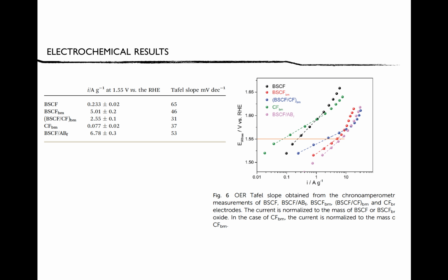They're saying that a surface layer with a short range order was created, and they are also seeing that there might be a hint of amorphization, and it has been a theory that amorphization of surfaces might be leading to increased activity. So there are these two surface related phenomena that we're looking at.